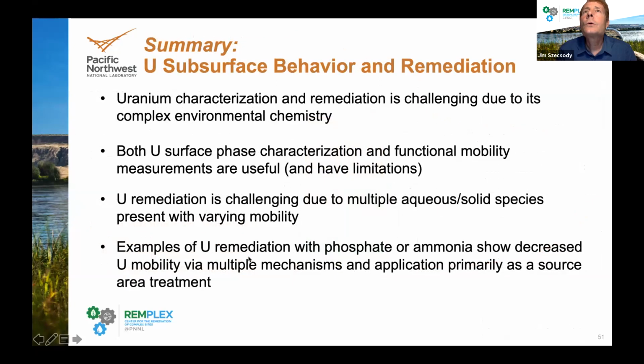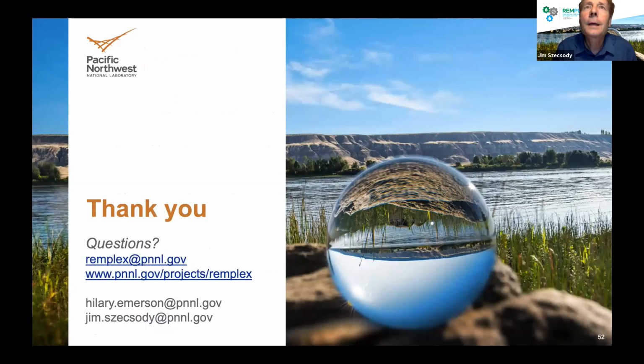Okay, so in summary, because uranium is present in multiple solution and surface phases with different mobilities, and co-contaminants are also present that alter uranium phases, remediation requires that multiple phases need to be targeted. The phosphate and ammonia remediation examples that I showed you both decreased uranium mobility, not all the way to 0, and there were multiple mechanisms involved. Also wanted to point out that these treatments are primarily for uranium source area and not permeable reactive barrier treatment. So thank you. Are there any questions?